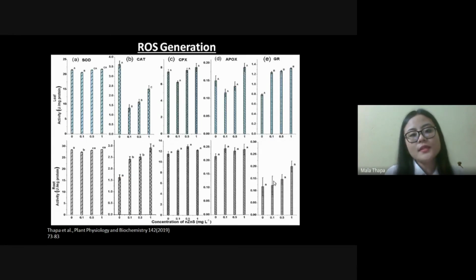Now, the role of zinc sulfide nanoparticle on ROS generation. Nanoparticle can produce huge amount of ROS and generate oxidative stress inside the plant. But in our case, none of the treatment produced any kind of oxidative stress. This is superoxide dismutase enzyme. This is a powerful enzyme of plant which catalyzes oxygen radicals to hydrogen peroxide. And we have found that at 0.1 mg per liter concentration of zinc sulfide nanoparticle, the superoxide dismutase activity decreased.